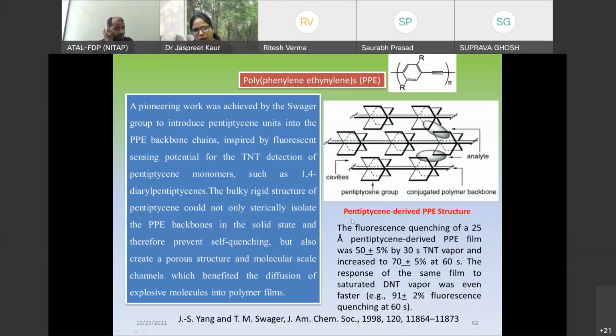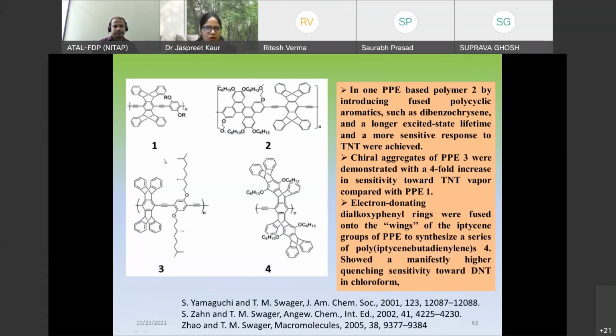You can see this is a pentiptycene derived PPE structure. This is the conjugated polymer backbone, and these iptycene units are arranged along the conjugated polymer backbone. This leads to a porous structure so that the analyte can bind in a better way, and this helps in the detection of TNT vapors. Now these are other PPE based polymers reported by the Swager group. You can see we have different molecules, 1, 2, 3, 4. This particular PPE molecule has better properties as compared to the previous one.